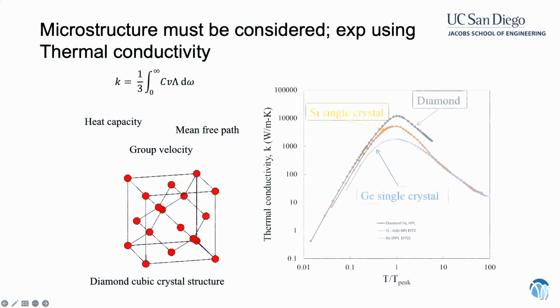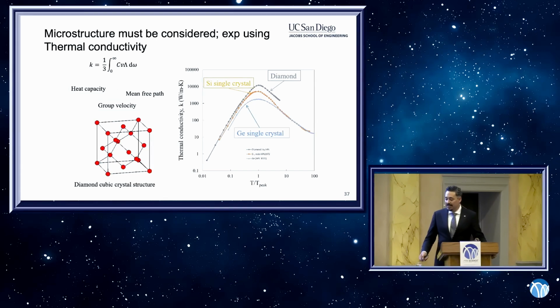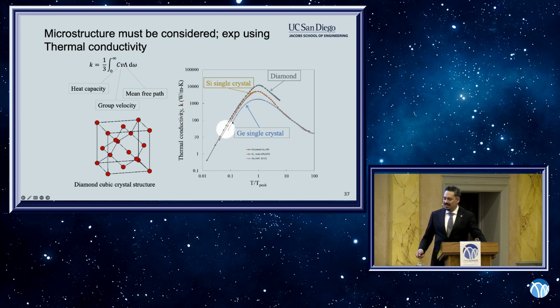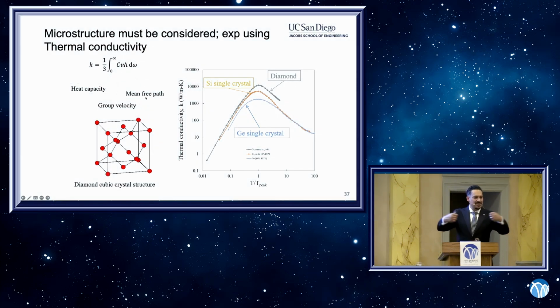Okay, so the thermal conductivity goes to 0 when you go to very low temperatures, and that's of course because the kinetic energy goes to 0, like I was talking about before. Now, as you increase temperature, your thermal conductivity increases because your heat capacity increases. This is a rise here. Then at some point you get a decrease in thermal conductivity, and that's because your mean free path decreases. You start getting scattering because you have more and more vibrations of the atoms, and they start scattering off each other.